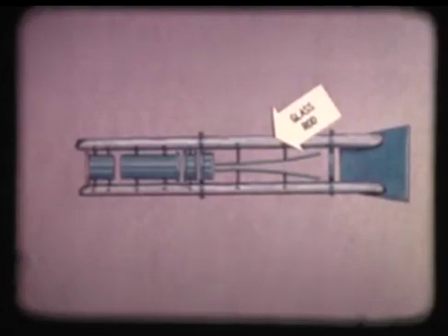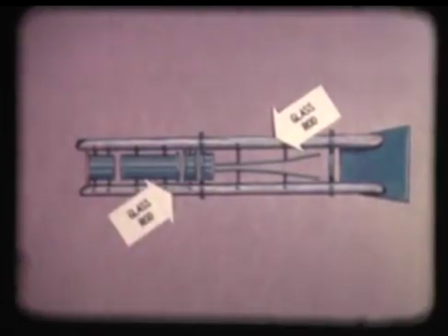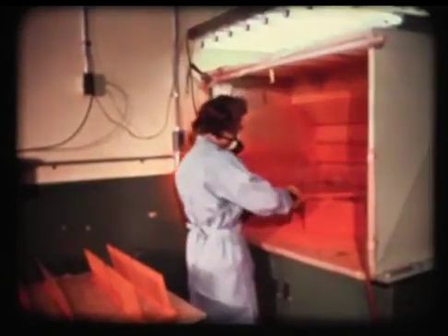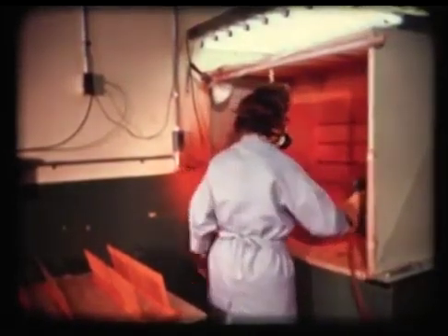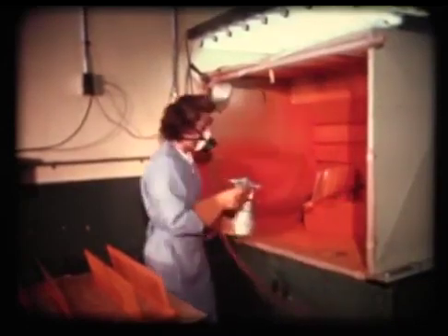Permanent, accurate alignment of the gun parts is best assured by fusing them into 4 glass rods. Pyrex glass gives the best dimensional stability, but because it's such a good insulator, it tends to pick up electrostatic charges which sometimes distort the trace. To overcome this problem, we lightly coat the Pyrex glass with lead oxide. During the process that follows, a microscopic layer of lead glass is formed on the outside of the rods. Charges do not build up on this treated glass.